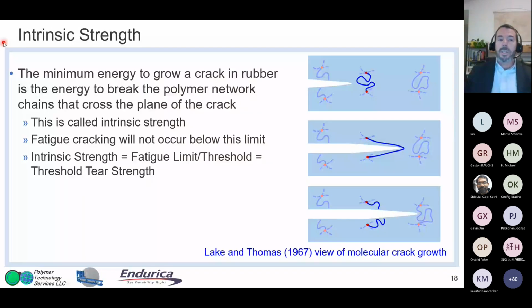Before I do, though, the intrinsic strength that is underlying this threshold is the minimum energy to grow a crack in rubber, which is connected to the energy to break the polymer chains. So if these are two cross links, and this is the portion of polymer chain that's between those two cross links, as the crack grows through the rubber, it has to break all of these sections between cross links in the plane of the crack. So if you want to know how much energy it takes, then you can add up all those chains and find out the energy to break the bonds. And that's exactly what Lake and Thomas did to relate it back to some molecular things that we can use to compare different elastomers, for example. But we'll get to that in more detail later.